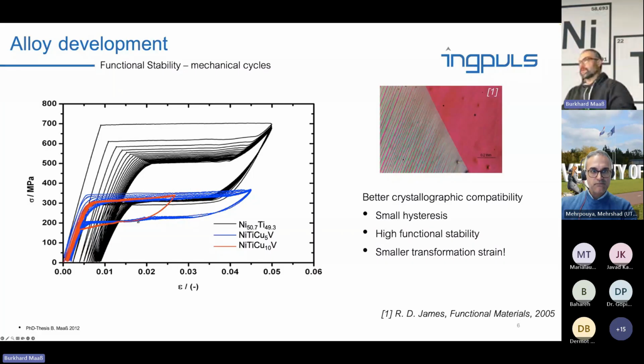Why is it so stable? Because of the crystallographic compatibility. That's the GNTM, the geometric nonlinear theory of martensite, where we learn that the small hysteresis stems from a good compatibility between austenite and martensite and having an almost perfectly coherent, I don't know the word for that, the habit plane, that's it.